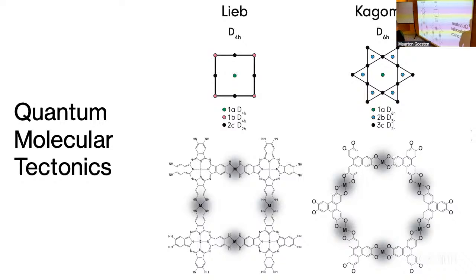So I will talk a little bit in a moment about this metal-ligand chemical bond, because to chemists, this is an unusual metal organic framework. In a typical metal organic framework, you have something like terephthalic acid. You lose the proton and then you get a metal-oxygen bond. You don't get a metal that way, right? So this is actually a conjugated system with induced diradical character. That's what I will talk about in a moment.